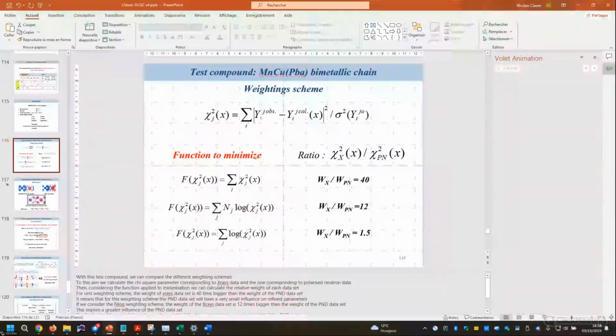If you see, I plotted there the relative weight of X-ray compared to polarized neutrons. If you use a very simple one, which is a summation of chi-square, you have a ratio which is clearly very favorable to X-rays, which is what you expect because you have significantly more data coming from X-ray diffraction. If you use the n log one, you will improve that balance. And if you use the log one, it's more or less the same relative weight for X-ray and polarized neutron. So playing with different weighting schemes, you can clearly highlight the role of the polarized neutron diffraction experiments. Thank you very much.